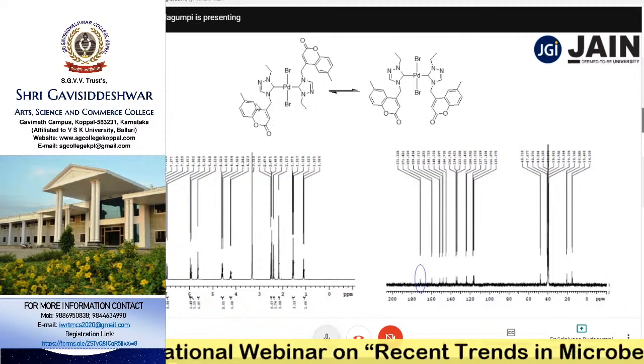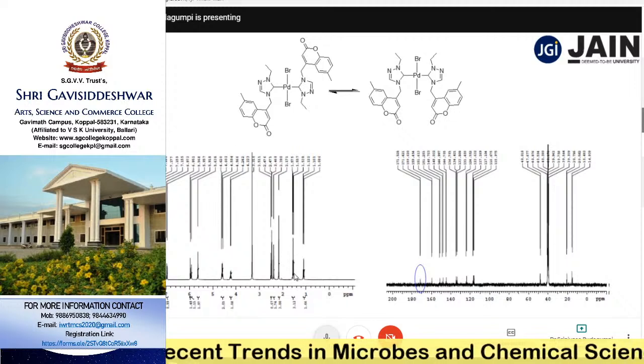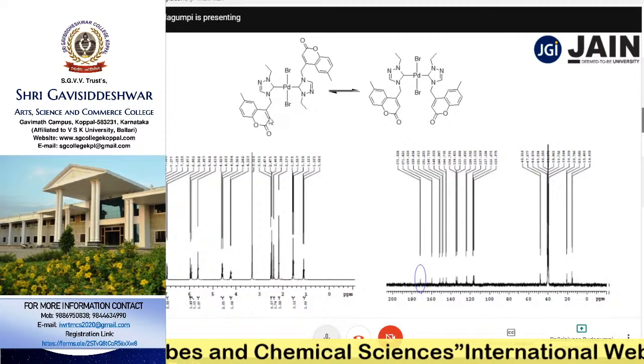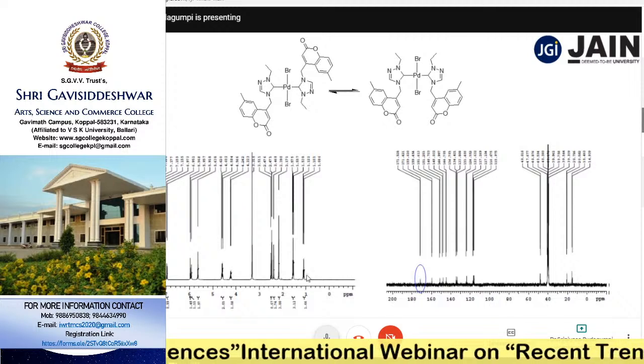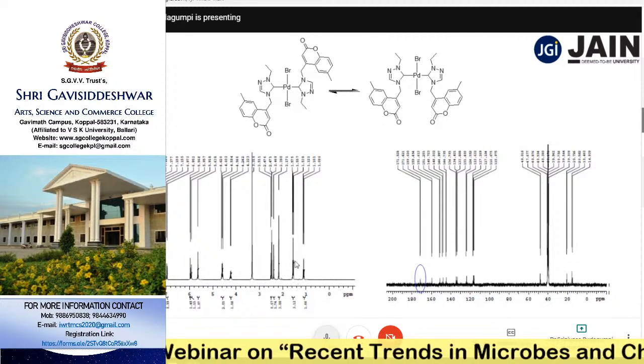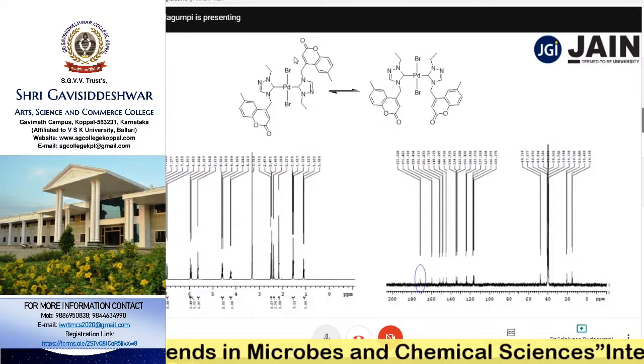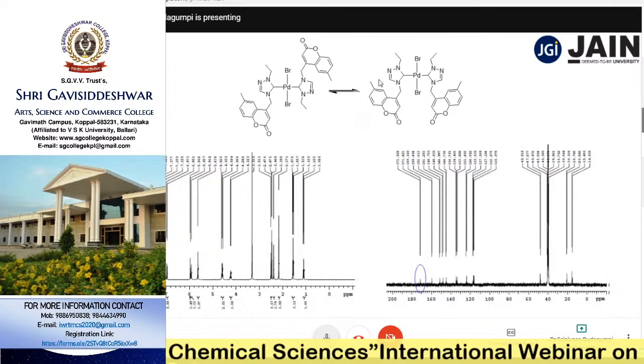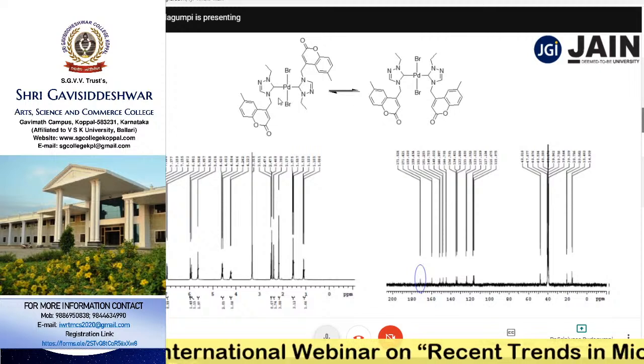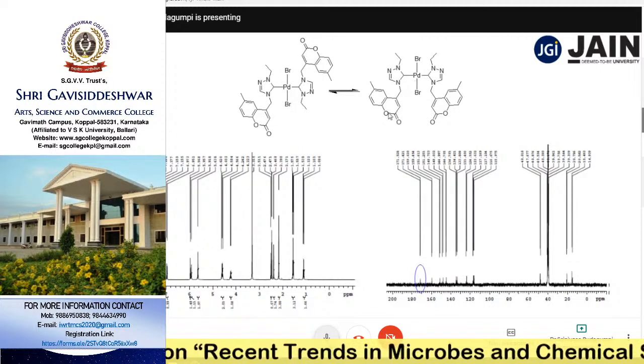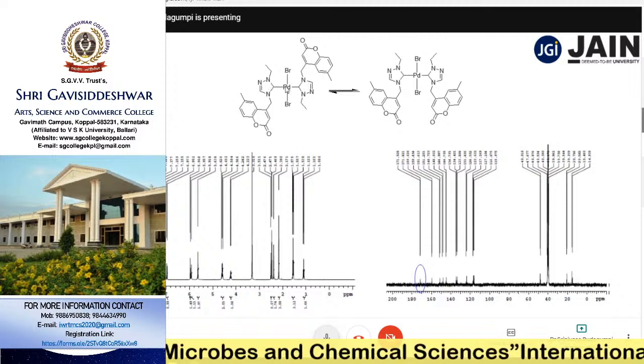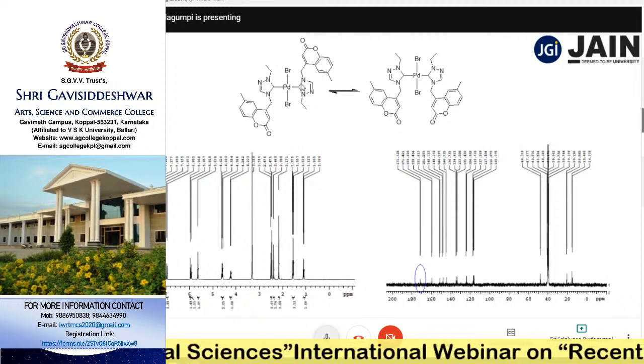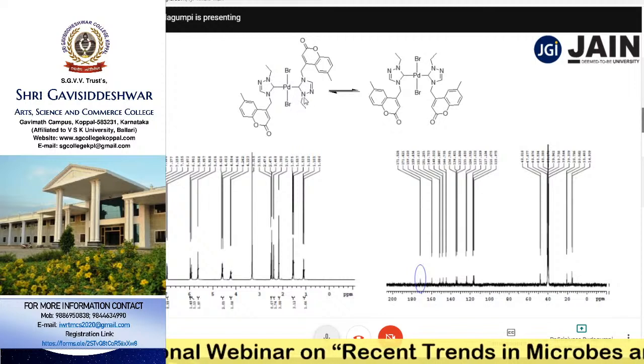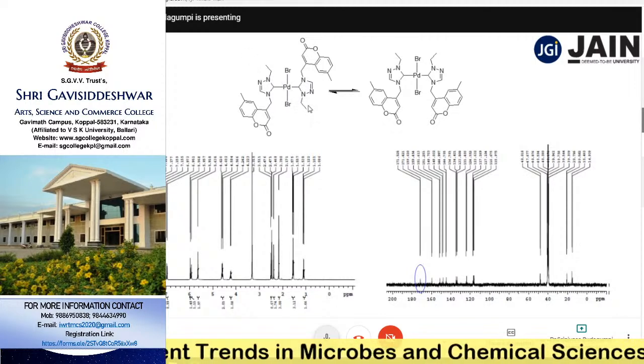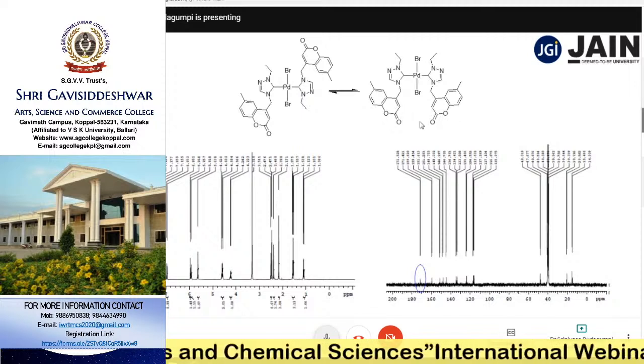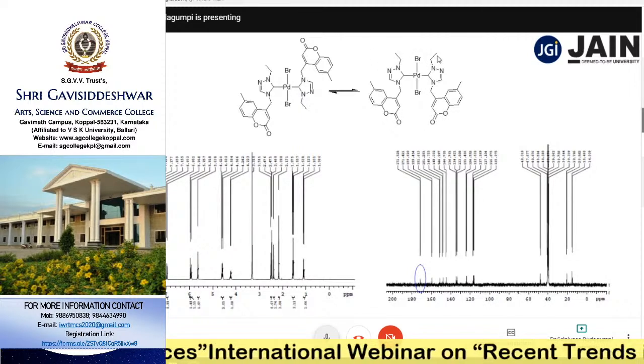Further, all the resonances corresponding to protons are in duplicates. Each and every proton resonance appears as sibling peaks. This sibling peak appearance is due to the dynamic behavior of the palladium complex in solution, which is attributed to the formation of rotamers. So this is a trans anti-rotamer, whereas this is a trans syn-rotamer. Look at the arrangement of NHC ligands around the metal center. These two substituents are opposite to each other, so we call this a trans anti-arrangement, while here both the coumarins are on either side of the palladium center, and these two alkyl groups are on one side of the palladium center.